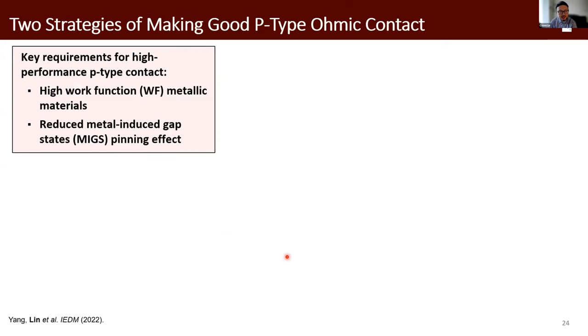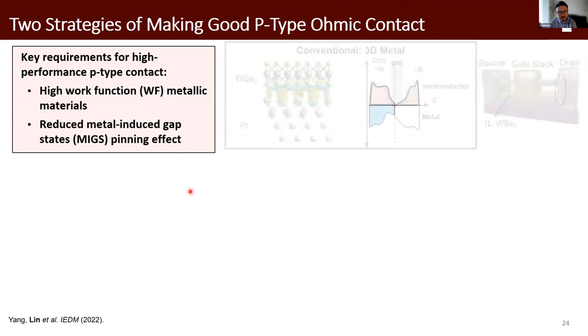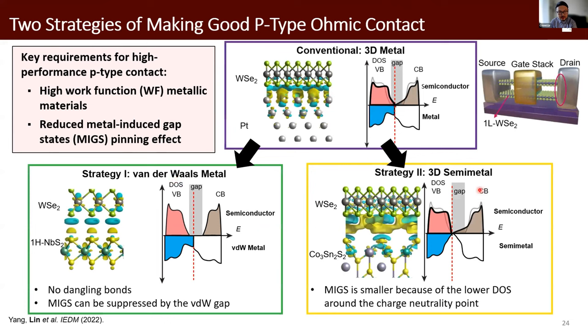Besides the high work function, there are additional requirements for forming P-type contact. As I mentioned earlier, we also need to deal with the Fermi level pinning effect or the metal induced gap states. So there are two approaches we proposed. One is to find a high work function semi-metal, so the low density of states point is aligned better with the valence band. The other one is we can use van der Waals metals, because of the weak van der Waals interaction, the metal induced gap states can automatically be mitigated.